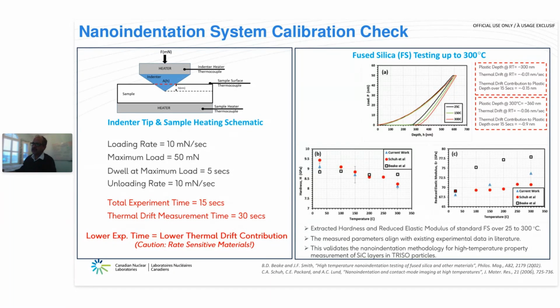So we performed load control tests to a maximum load of 50 millinewtons, and I'll come to why we chose this specific value. It was used for fused silica as well as for our silicon carbide coatings. Results I'm going to present subsequently. So the load control indentations were up to a maximum load of 50 millinewtons. The loading rate was 10 millinewtons per second, and the dwell at the maximum load was 5 seconds, and subsequently the indenter was unloaded at the same rate, 10 millinewtons per second.